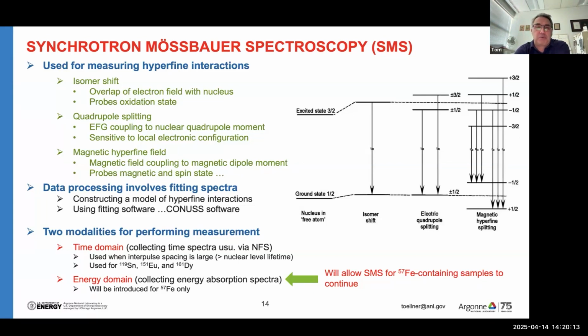Now, unlike the vibrational spectroscopy, where you can extract information straight away from the data without fitting, though you can also fit it using DFT, and some users do that depending on what kind of information one wants to attain, in the case of Mössbauer spectroscopy, one has to construct a model of the hyperfine interactions in the sample. And so each nuclear site needs to have a set of nuclear parameters defined, and then one can generate a spectrum, and we have fitting software that does this. This is CONUSS software, and that is used by the users to fit the data.